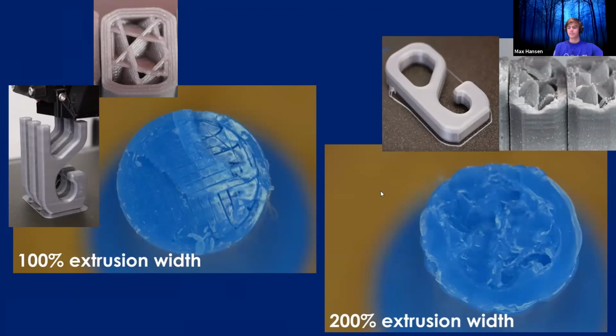In this example at least, the way they chose to fix it was by upping the extrusion width to about 200%. And as you can see in this image, the plastic is much better bonded together, and it looks almost like a molded part. You can see here it just tore straight across the material here, and there's no flat cut. It's jagged, similar to this XY rip here. So whenever your part breaks, you want to be going for this jagged and sort of uneven look when it comes to breakage.